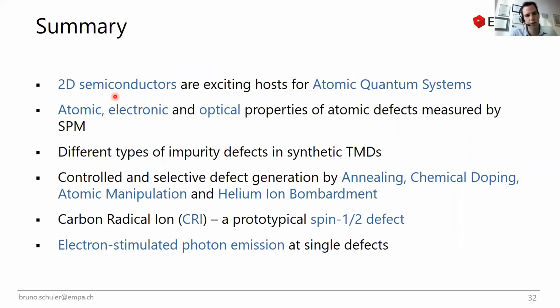So I hope I could show you that indeed these 2D semiconductors are a quite nice and versatile platform to engineer and probe atomic quantum systems. We looked at atomic, electronic, and optical properties at individual defects measured by different means using scanning probe methods. And we characterized in detail the different types of impurities already present in synthetic TMDs without doing anything to them. So that's just a fact of how they are. But then we also tried to find different ways how we can controllably and selectively generate those defects by, for instance, annealing, chemical doping, atomic manipulation, and helium ion bombardment.